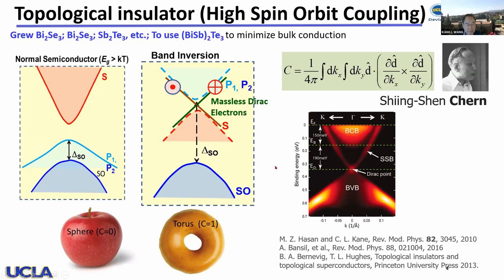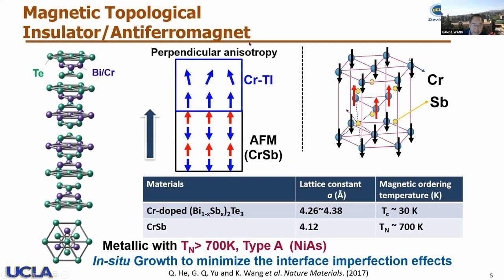We use this material first to interface with an antiferromagnet to look at the exchange coupling. If we introduce chromium doping — I call it BST now — bismuth antimony telluride of the topological insulator, it has a Curie temperature of roughly 30 K. We choose chromium antimony as the AFM, which has perpendicular magnetic order, and we pick this because we can grow it in the same chamber without interface issues.